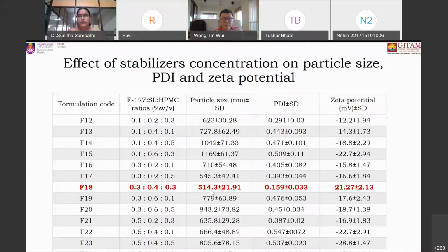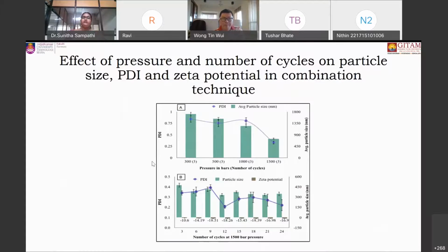Hence, we have carried out this particular formulation as an optimized formulation for further studies. Now, the formulation which we have optimized using the sonoprecipitation technique was taken for the combination technique. In the combination technique, for the optimized formulation, initially we checked two process parameters. The first one is the pressure. We varied the pressure from 300 bars to 1500 bars for 3 cycles.